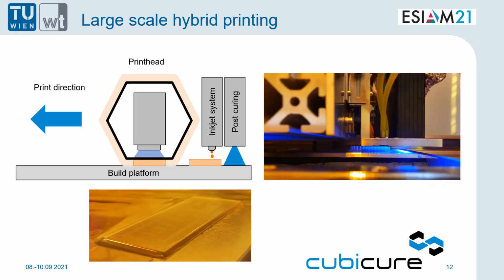In this project, we extended this large-scale Cubicure hot lithography system with a fully functioning inkjet system, including fluid delivery, printheads, as well as a post-curing unit, which allows us to cure the selectively placed ink droplets on the substrate. After curing of the SLA layer, the part surface comes off dry and clean, as you can see here, which is obligatory if you want to jet on the substrate.